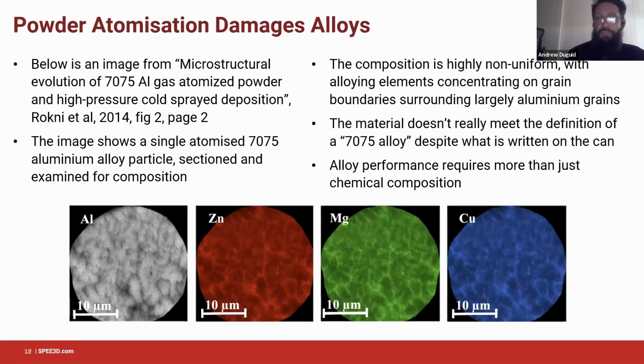And what that means is that we're left with a powder that's not actually particularly sympathetic to being sprayed. It's not to say that you can't do it. Obviously, people do it all the time, but you have to go to a higher degree of effort to overcome those sorts of problems. And indeed, another avenue that people explore is resolutionizing those particles and rendering them into a softer state. Also a good way of solving the problem. But we take a slightly different approach to that, by and large, and so we might move on to the next slide.